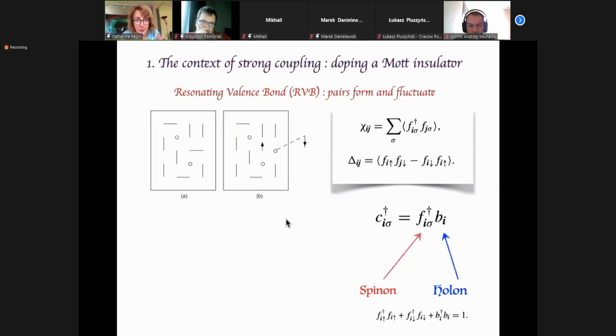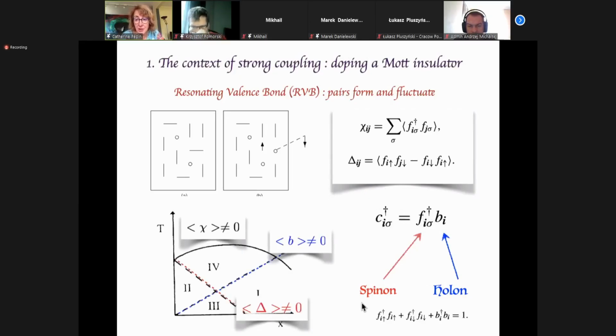So let's go a bit more into detail. The first one, strong coupling, was the prominent theory, basically put forward by Phil Anderson, who, not even a few months after the discovery of cuprates, put forward this very brilliant and unusual idea of a resonating valence bond. So pairs form at different distances, superpose themselves and fluctuate. And this would be Anderson's solution of the pseudogap. So it's strong coupling. It would mean that the electron is fractionalizing into a spinon and a holon. And this is protected by a constraint, which ensures that the number of degrees of freedom per site is conserved. Here, the spinons are represented by fermions and holons by bosons, but you could reverse the representation. And you have an emergent gauge field, U(1) in that case, but you could have an SU(2) version of it.